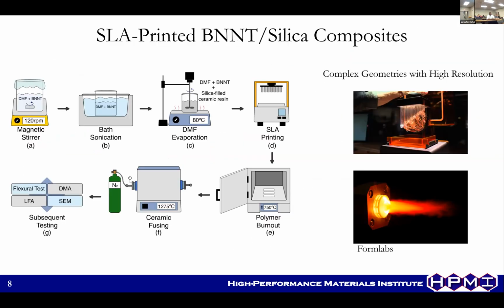So is there anisotropic regions within the end product that you print? Layers that it might delaminate along? With this very low level of additive, we did not see that. You would probably see that with higher levels of additive. This is not extrusion 3D printing, so you wouldn't expect any orientation. You would just expect to hold whatever suspension orientation you have, and then you're just freezing it in place.